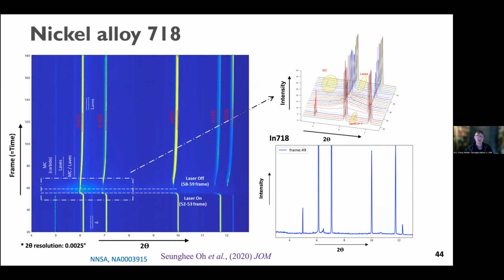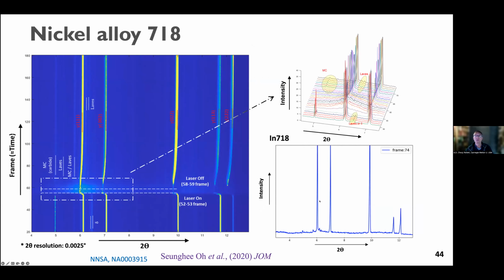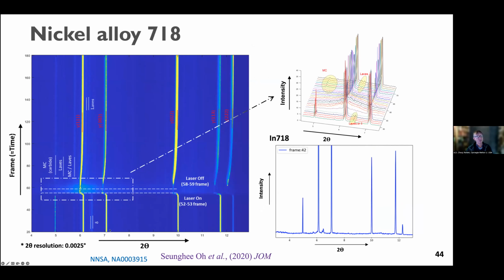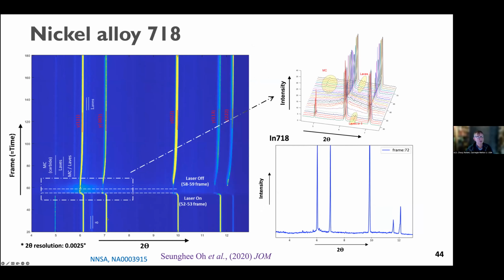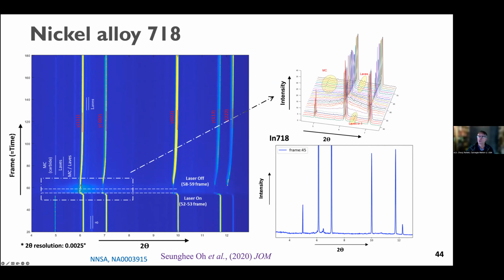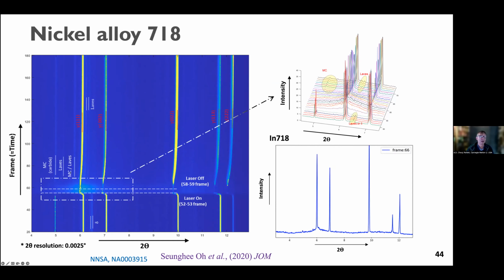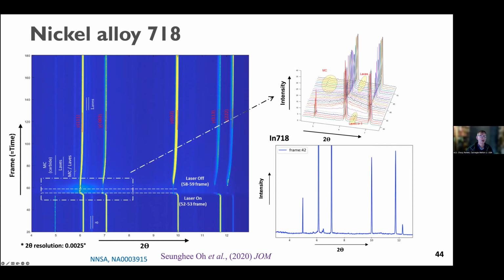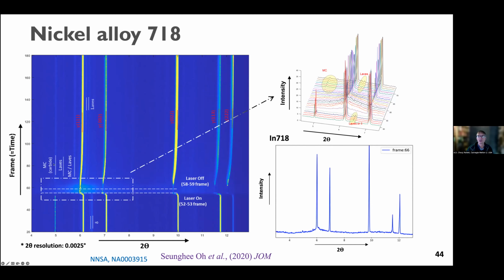So if you take those rapidly evolving diffraction patterns and you integrate around the azimuth, you can reduce it to this sort of streak diagram picture. And the time zero is at the bottom. And so time goes by, it melts, the diffraction lines disappear, however briefly. And then obviously the matrix, the FCC matrix reappears. But what you also notice is that some phases appear that were not there at the beginning, particularly the Laves phases. And you also get certain carbide phases. So carbon is present at a small fraction.